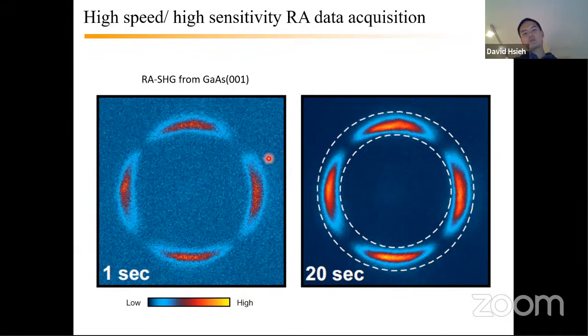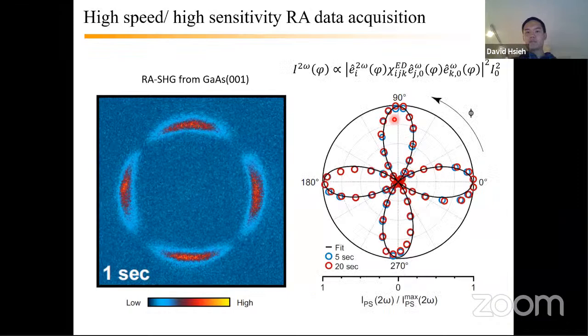And so here is data from gallium arsenide, which is a nice sample to work with. And you can see that for gallium arsenide, which breaks inversion, we have a strong electric dipole SHG allowed in the bulk, you get these patterns within seconds. That already manifests the symmetries of the underlying material. And to quantitatively analyze these data, we just radially integrate between these dashed lines where the data is non-zero and form these polar plots, okay? The radial direction here is the intensity versus the scattering plane angle.